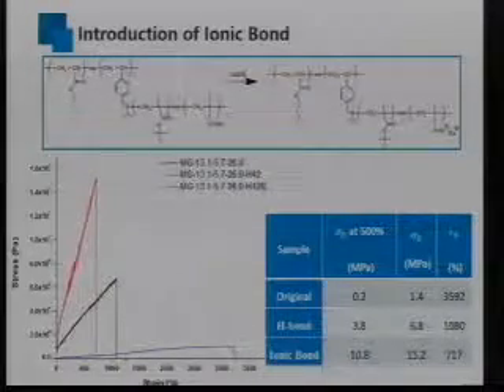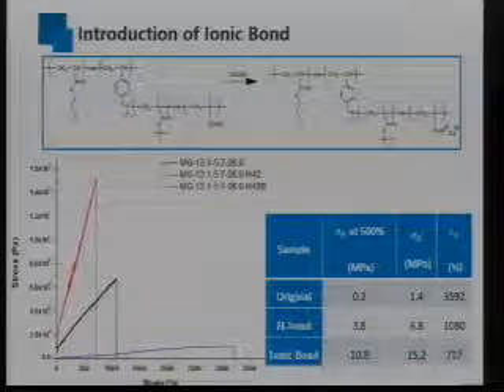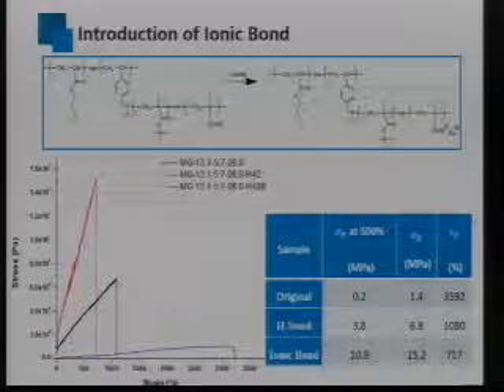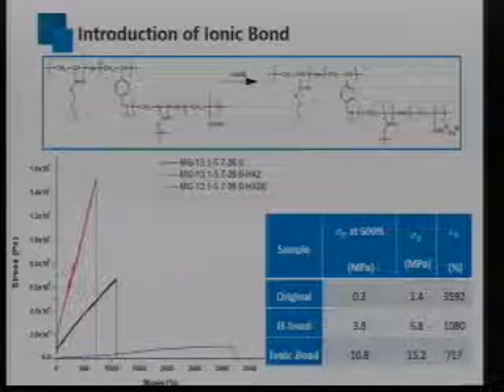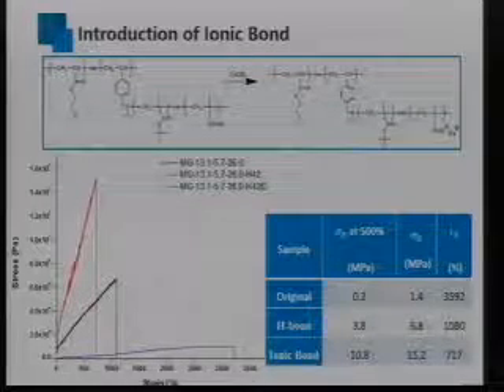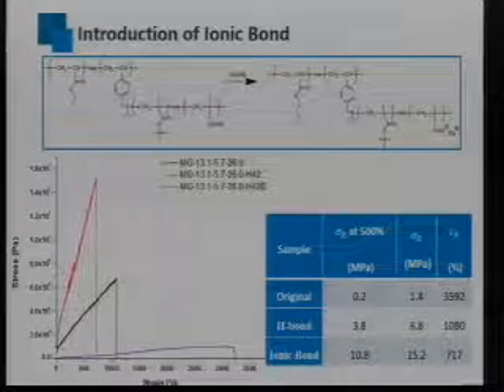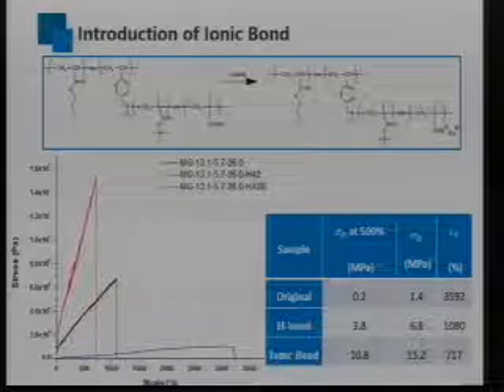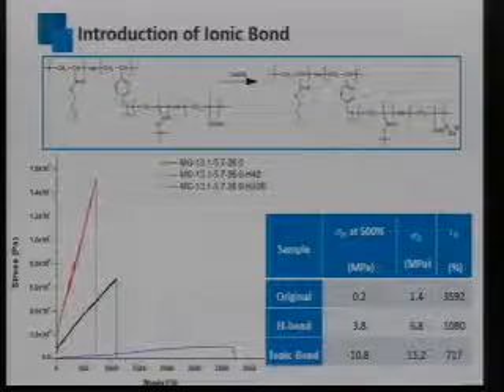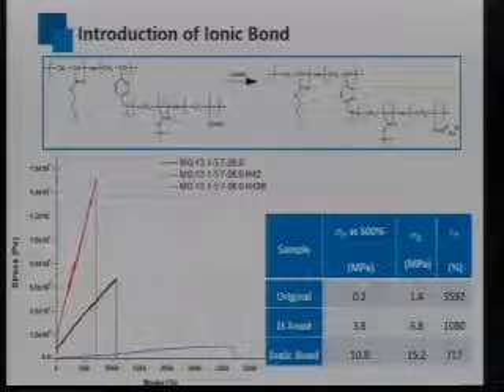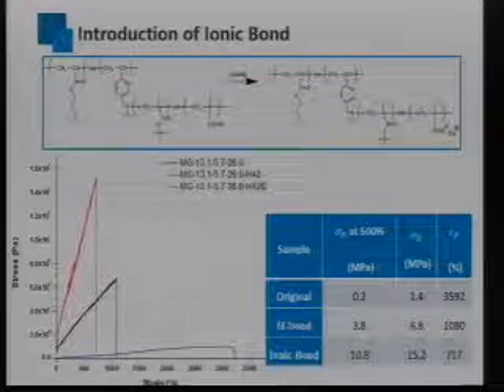The further modification of this material was performed by the introduction of sodium hydroxide to change the methacrylic acid into the ionic type. In this way, we introduced the ionic bond. So for the hydrolysis degree of 42%,